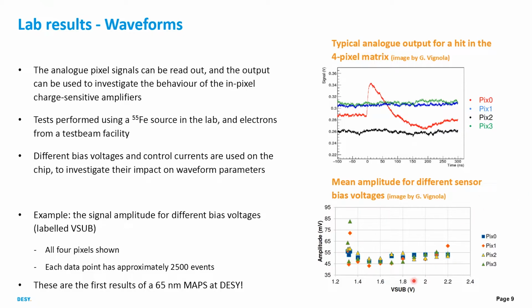And here's an example study where we studied the signal amplitude versus the bias voltage, the back bias, labeled V sub here. And this shows all 4 pixels, and each data point here is approximately 2,500 events. And one might be able to extract some little trends here, but there's not much, it's rather flat. But importantly, this is just an example, and these are the first results of a 65 nanometer MAPS sensor at DESY, which is very cool.